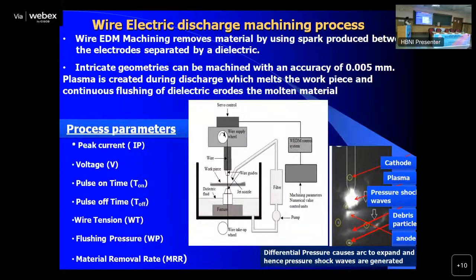EDM is actually a machining technique where you remove materials by using sparks produced between two electrodes separated by a dielectric. Intricate geometries can be machined with an accuracy of 0.005 mm. Plasma is created during discharge, which melts the workpiece, and continuous flushing of dielectric removes the molten material. So this is the schematic diagram for EDM. You have the two electrodes. One of them, of course, is the material itself, and you have the melting and removal of material. So local melting and removal of material. And you have the material coming out in form of droplets.